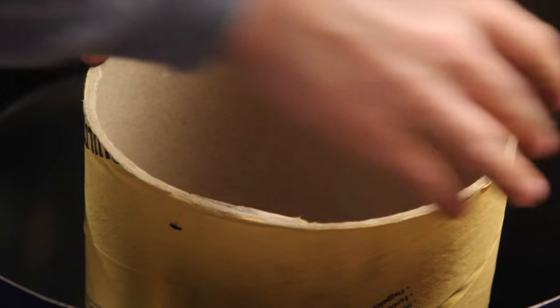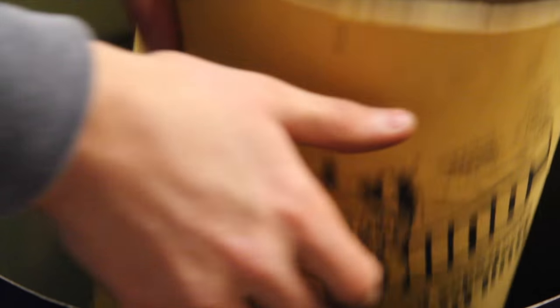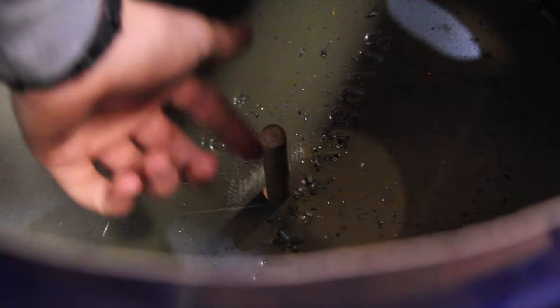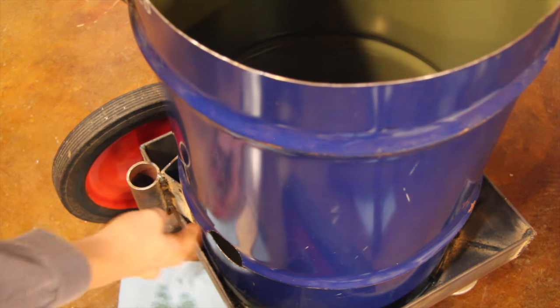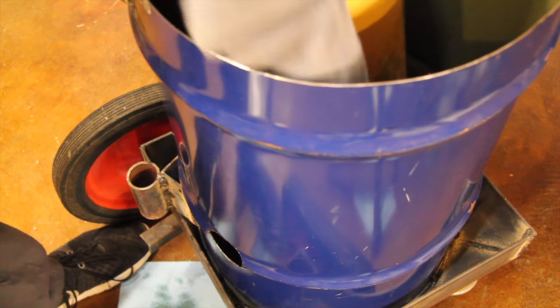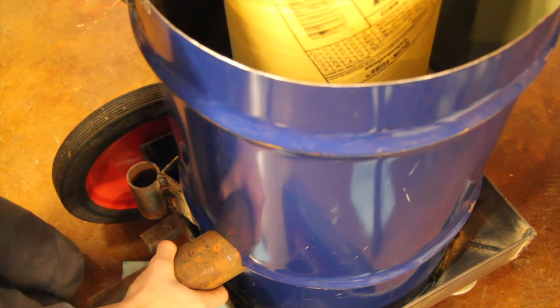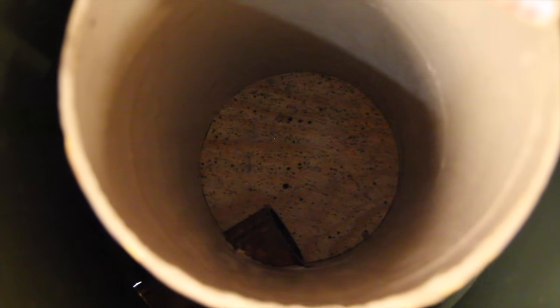We just cut a cardboard tube so that the concrete will form around the outsides and there will be a hole for the fire and the crucible to go in. We also have a plug in the bottom with a small little dimple so the concrete doesn't come all the way up because we're going to do it in one pour. We cut this dowel here to where it sticks up from the bottom of the barrel three inches. It serves to define how much concrete will be on the bottom layer, and so if there's a crucible failure, the molten metal will just fall down this absence of concrete. We also drilled a hole in the side of the bucket and this little tube to accept the burner pipe. The pipe being offset like that is actually quite important because when we put our crucible in, it doesn't go straight into the side of the crucible and just burn a hole into it. It will also get a swirling effect that will get the heat around the entire furnace.